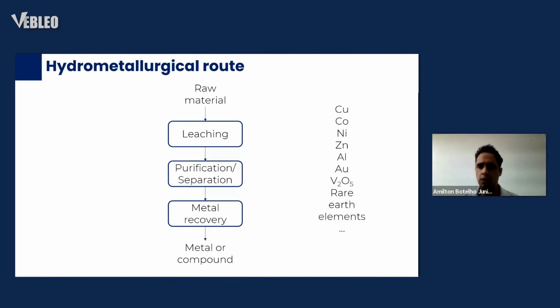So how does it work? The raw material, in this case the e-waste, after the physical process, is reacted with a leaching agent. A leaching agent is a water mixture that may be acid or alkali. So it can work in acid media or in alkali media to dissolve all those elements into the aqueous media, to be mixed with water.